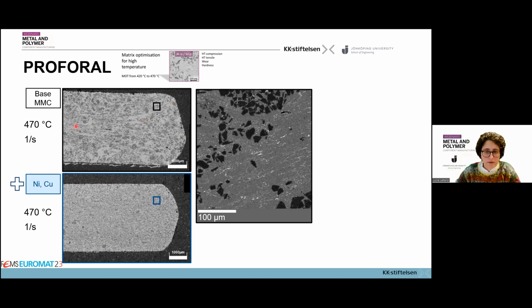You see how the material got deformed under pressure, and it flowed away to the sides of the sample, and we had a little bit of extrusion here on the external side. But you see clearly how both the matrix and the carbides are moving, following the flow of the material. And here you see in high magnification the dendrites of the matrix, and as a consequence also the eutectic silicon, get stretched and heavily deformed to accommodate the pressure that is given during the compression test.